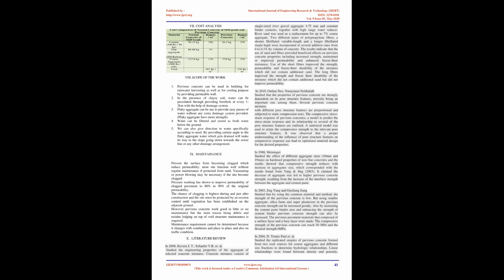9. Maintenance. Prevent the surface from becoming clogged, which reduces permeability. Most sites function well without regular maintenance if protected from sand. Vacuuming or power blowing may be necessary if the site becomes clogged. Pressure washing has been shown to improve permeability of clogged pavement to 80% to 90% of the original permeability.